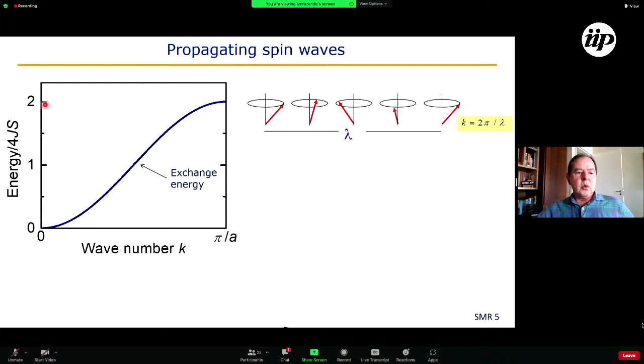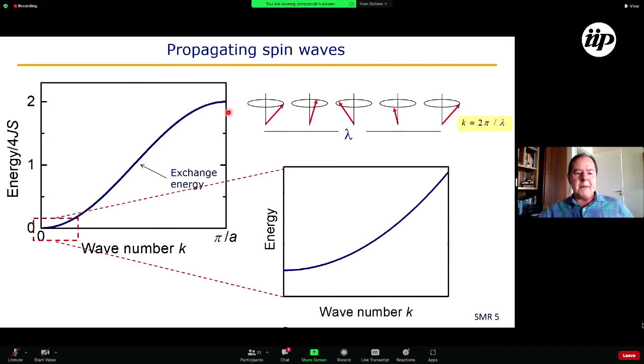So if we solve the equation for the whole Brillouin zone, we have that the energy frequency increases with the wave number. For small wave numbers, it varies quadratically with the wave number, but then it curves like this. And if we zoom the figure here, we have a quadratic behavior, as I said, very similar to what happens to electrons. Omega is gamma times H plus d k squared. Gamma is 2.8 gigahertz per kilo-oersted, which means that with fields of a few kilo-oersted, the frequency of the k equals 0 mode is in the microwave range.